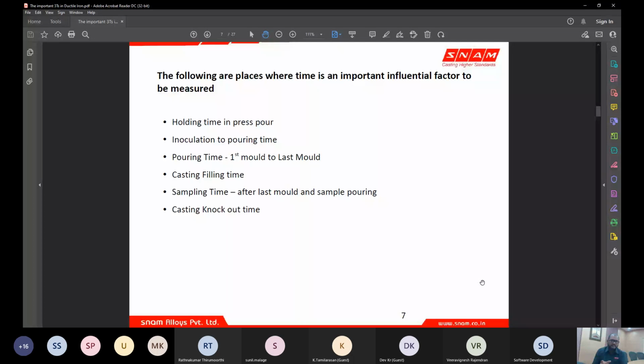So the time in which the nuclei form and are sustained for a longer time depends on the time taken after addition. So if, for example, you add your inoculant at the latest stage, say after the first transfer and second transfer, you do an inoculation closer to the furnace and your transfer is 2 times, and then after 3 minutes or 4 minutes, you start pouring into the mold.